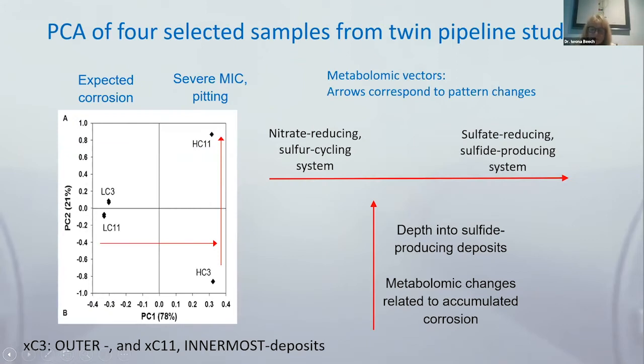What we found in this first shot at the Norwegian studies is that we had a very distinct difference in metabolomics, confirmed to some extent by metagenomics, between the corroding and non-corroding pipe. LC is low corrosion, HC is high corrosion, and numbers are designated to pig envelopes. Pig number 11 is the pig that was closest to the metal surface. Pig number 3 was the third pig that they pushed through the pipe to remove the corroding material and deposits that were accumulating in the pipe. LC is low corrosion and the corresponding pigs from the pipe. In metabolomic space, they were very, very different. And as was confirmed later by more sophisticated data, high corrosion pig 3 was like day and night from high corrosion pig 11.